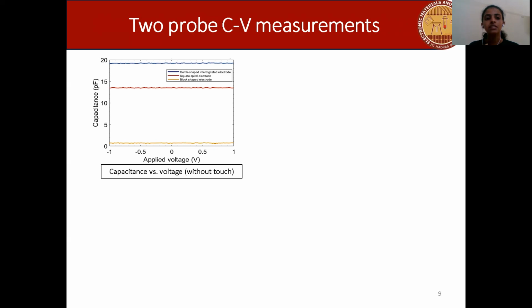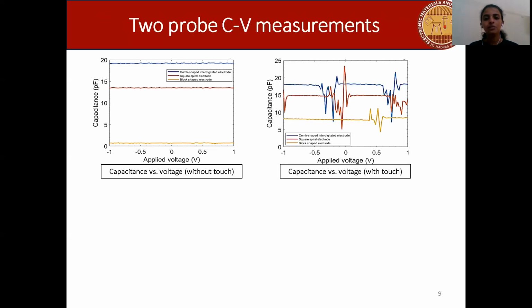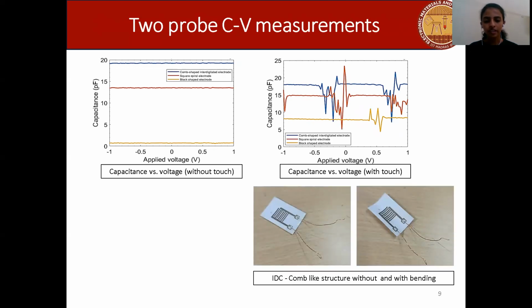This can be probably because the structure is not as intricate compared to the other 2 structures. And in case of simulations, we did not have to make so many approximations when compared to the other 2 designs. Now, if we observe how the capacitance is varying with touch, in this case, we can see that similar to the earlier case, the interdigitated comb-shaped electrode structure was showing a larger capacitance and also a significant variation in capacitance when the device is touched. These are the 2 structures of the interdigitated comb-like structure with bending and without bending that I have fabricated experimentally and measured.